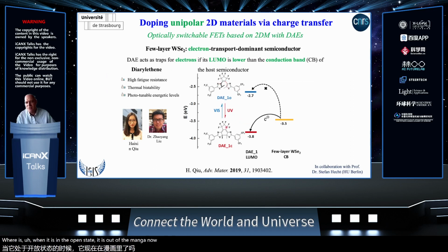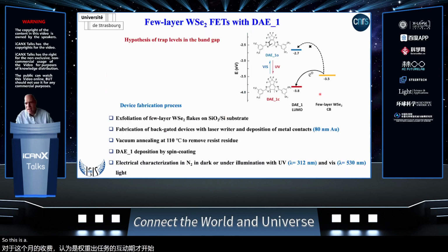Now, what does this mean? When a state is in the band gap, it acts as a trap for the charges of the semiconductor. When it is out of the band gap, the interactions are purely electrostatic. So that's the overall idea. We fabricated a transistor by exfoliating the tungsten diselenide, a few flakes thick.